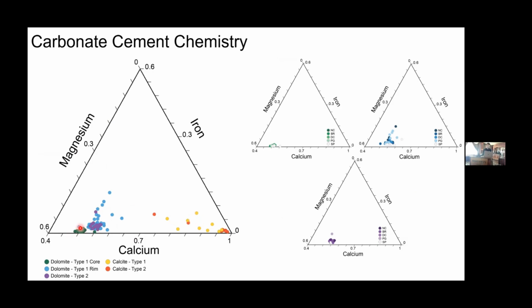And so you'll see that the type 1 cores plot nicely at about the stoichiometric line for dolomite, so 50% magnesium, 50% calcium. And then as we move into those rims and to the type 2 dolomites, we see an increase in calcium and iron relative to the core, which is exactly what I mentioned in the EDS maps. And then looking at the calcite cements, the pore-filling phase typically has a lot of iron and magnesium associated with it. And the replacive phase commonly plots almost 100% calcium, with the exceptions of where it's replacing dolomite in these two instances.